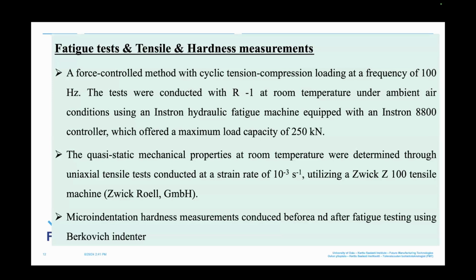Of course, we started fatigue tests under force control with stress ratio R of -1 using an Instron 8800 controller. We also have this very strong machine with a load capacity of about 250 kilonewton. After that, we studied the mechanical properties using quasi-static tests on a Zwick machine, strain rate 10^-3.